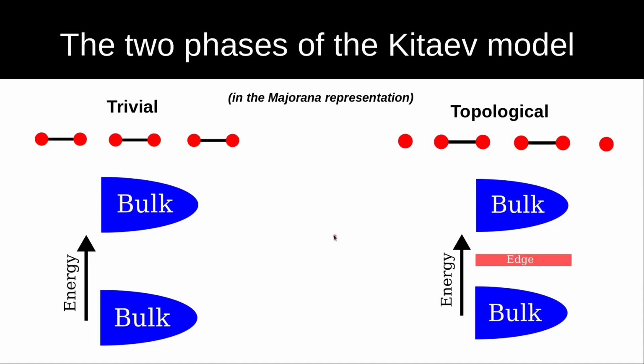And so in practice, in the case where you have fine tuning, so delta is equal to t, there's no chemical potential, you can actually show that the Hamiltonian can be mapped in the Majorana representation to the dimerized model that we saw in our recording for topological physics. And in particular, the two uncoupled Majorana modes correspond to this mode at the beginning and this mode at the end. So you can think that in the Majorana representation, this one-dimensional topological superconducting model effectively maps to our dimerized model where we had strong coupling between two sites and no coupling whatsoever between the other two sites.